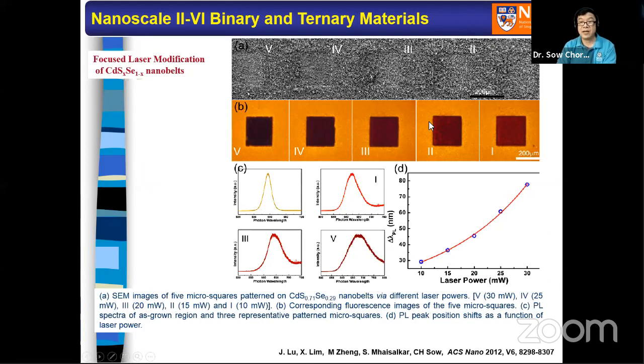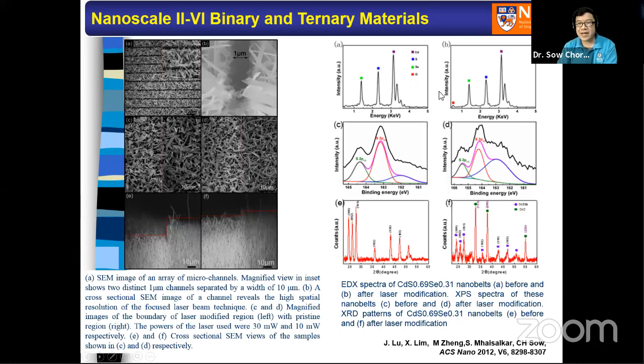These are all fluorescence imagings. The color of the original nanowire is orange. But after laser modification with different power, you can tune from red to dark red. So what is going on? The wire is CdSSe. So the moment you shine the laser beam into it, and we have data to suggest that, what you do is that you are actually tuning the sulfur selenium proportion in this particular material system.